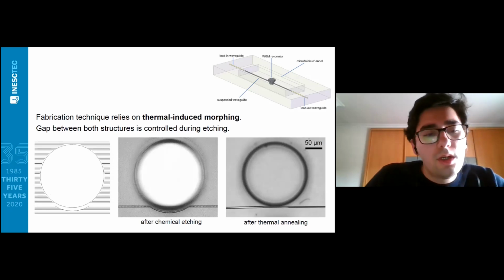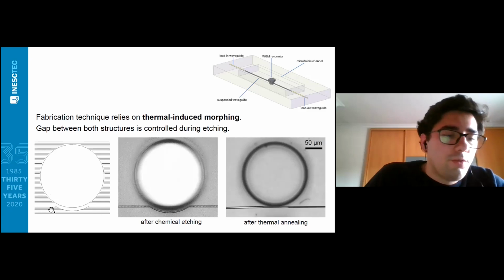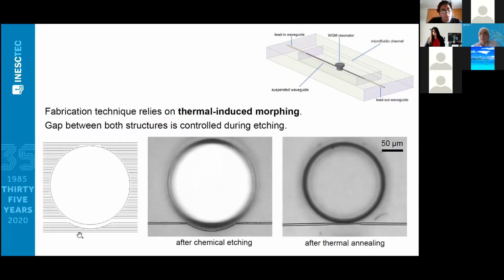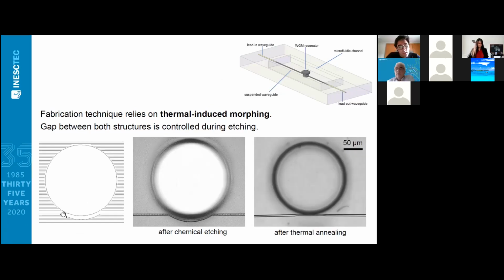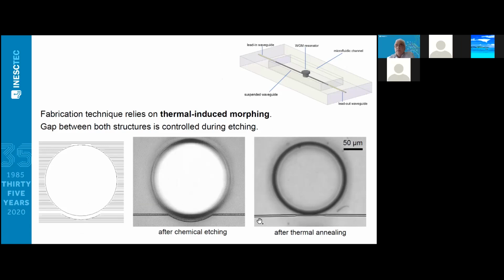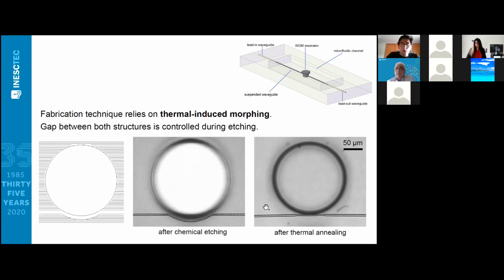After a lot of work, we have observed that the best way to write it is to fabricate the waveguide a bit embedded within the microdisc, but with an arc segment that follows the disc's curvature. After chemical etching, you also have a gap between both structures, but as you can see here, after thermal annealing, viscous induced flow will cause the waveguide to realign itself, and if we do things carefully enough during etching, we can have the waveguide end up tangent to the microdisc as shown here. Not only that, in the design, if we change the width of the arc segment, we can also shape the waveguide within the coupling region, and this way we can maximize even further